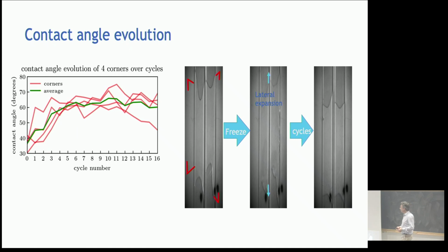And then the question is, what is the effect of the cycles? And what we actually find is that the contact angle that the liquid makes with the wall of the capillary actually tends to increase with every cycle on average. And so what you should realize is that during freezing, the contact line moves, and then during thawing, during melting, the contact line retracts, but the retracting contact angle of water on these capillaries is probably high, and so we get a contact angle that increases with the number of cycles. But it's more complicated than that because there's actually freezing happening in between.